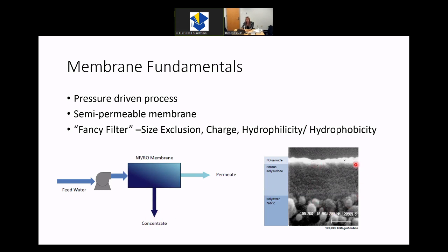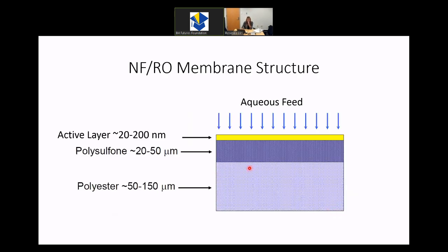Here you have an image to get an idea of the thickness of the polyamide layer with respect to some of these polysulfone and polyester layers, and the density that's associated with those. So, the nanofiltration or reverse osmosis membrane structures typically have three layers. They have an active layer, which is about 20 to 200 nanometers in thickness. They have a polysulfone layer, which is between 20 and 50 micrometers in thickness, and the polyester layer is between 50 and 150 micrometers in thickness. So the aqueous feed, or the dirty water, would come in contact with the active layer and permeate that way.